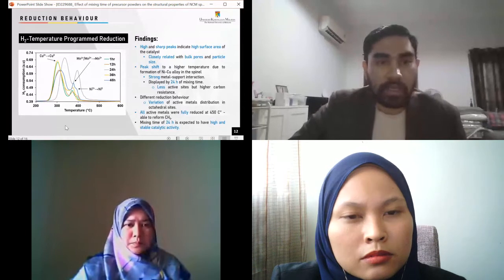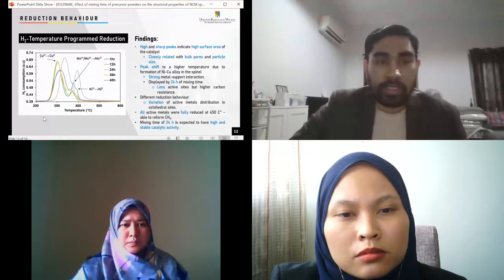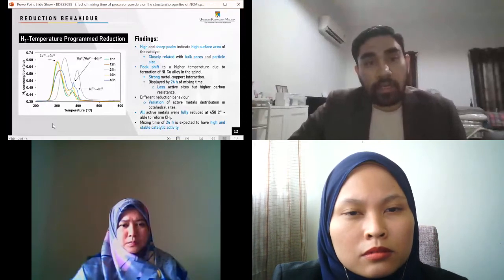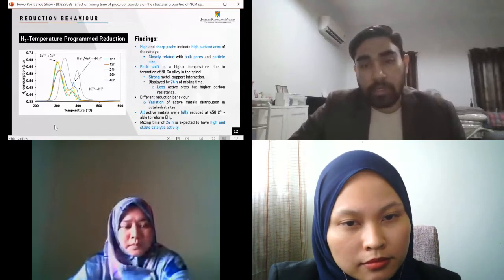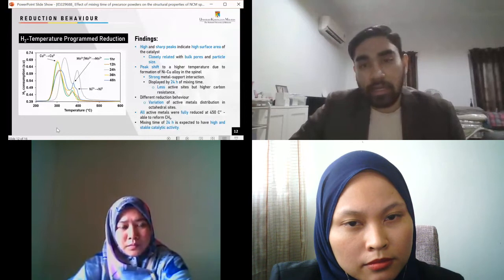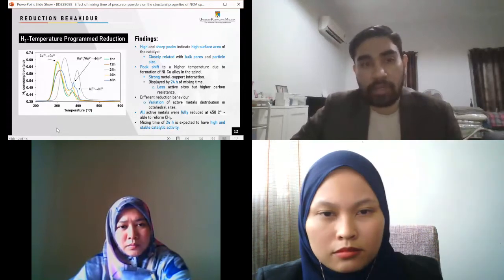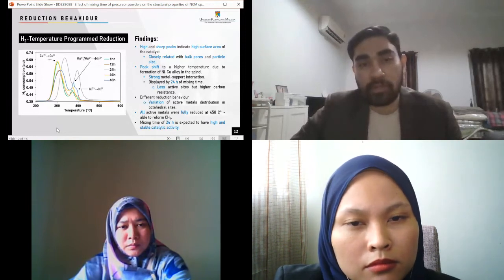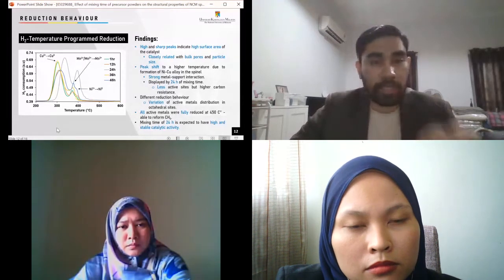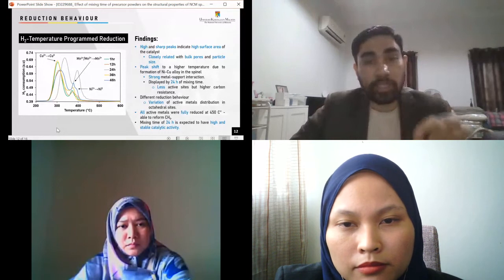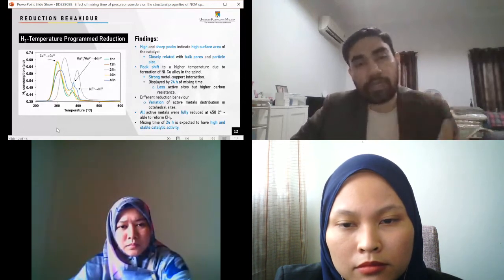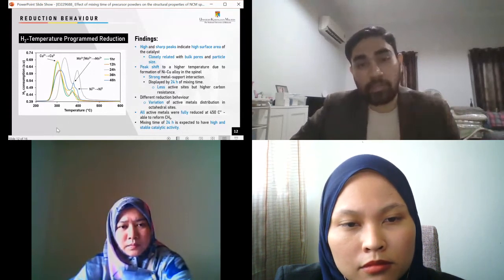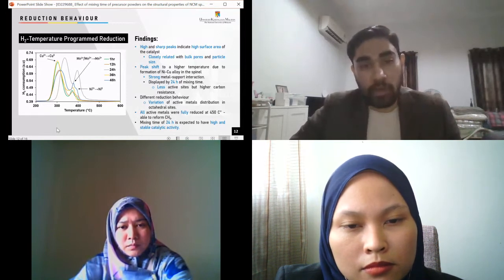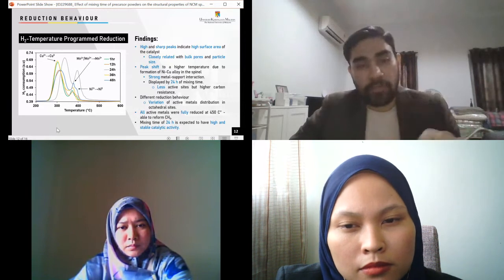For these figures, the three main things that we have to observe are the intensity of the peak, the location of the peak, and also the peak shift. Here we can see that the high and sharp peak was indicated by the 24 hours mixing time. It shows that this spinel has the highest or the fastest absorbance of reactant, which can help in fast methane reforming. Also, the peak shifts towards the higher temperature for 24 hours mixing time, indicating that this particular spinel has a strong metal support interaction, which can help in increasing the stability of the catalyst. It also has the highest intensity, which indicates a phenomenon called hydrogen spillover, which also helps in increasing the catalytic activity of the catalyst.